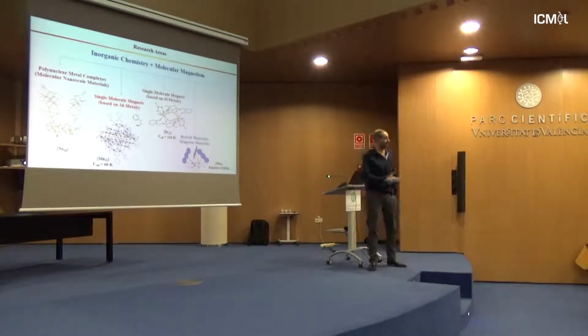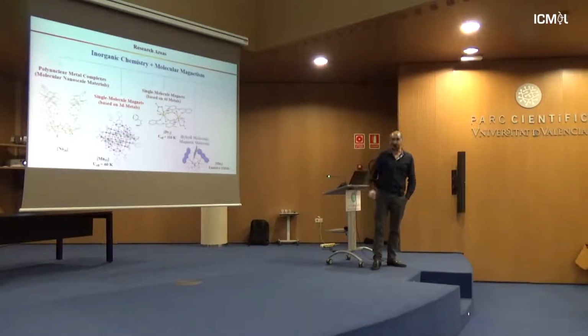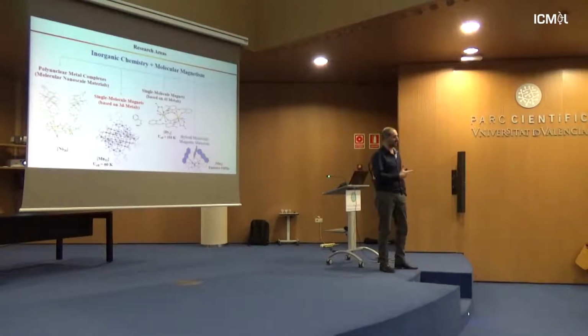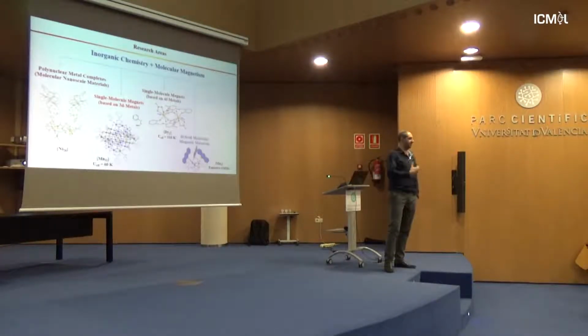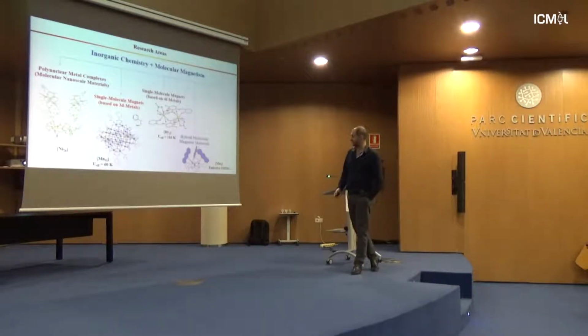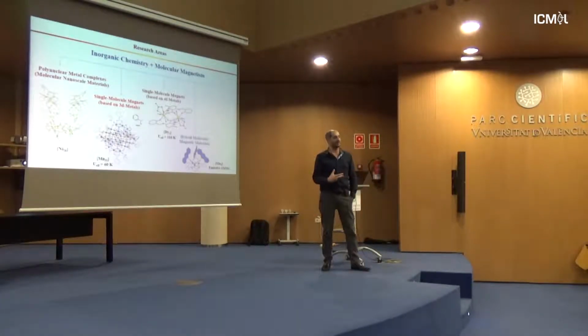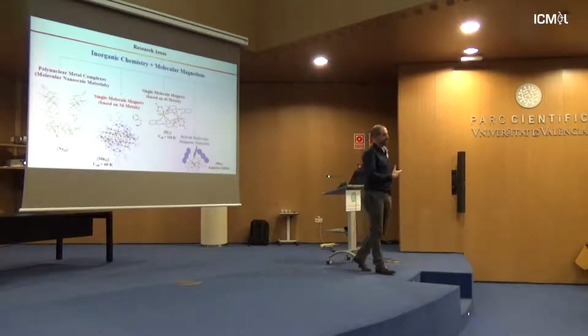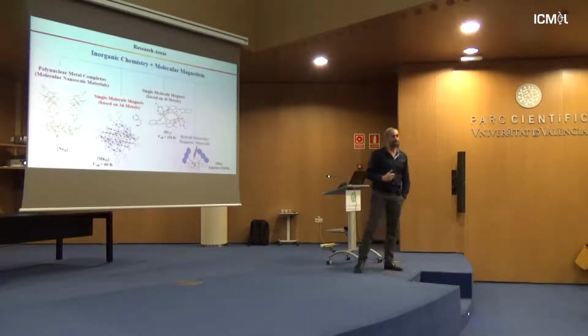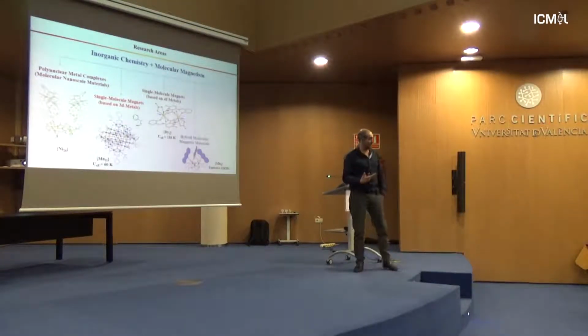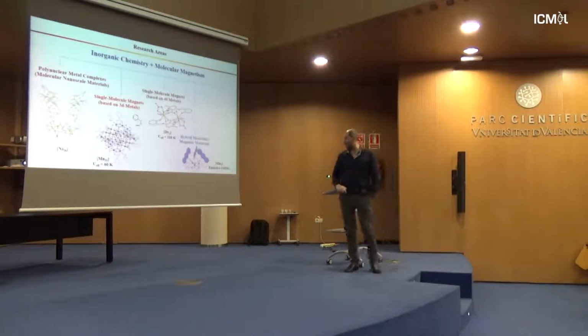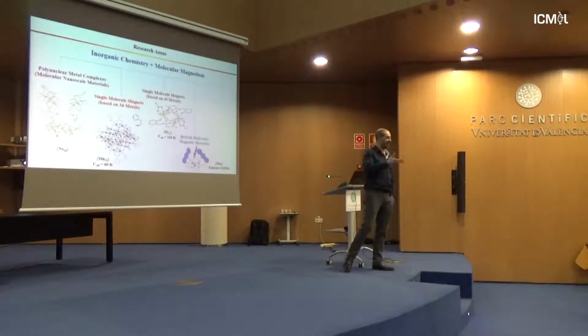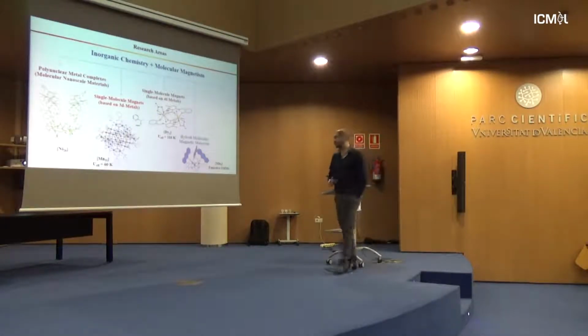And what we've found out from these compounds is that they still retain their photoluminescence properties. They emit in the red and blue regions of the visible part of the electromagnetic spectrum, while they still retain their SMM properties without changing the SMM dynamics. So the next thing that we would like to try, but we don't unfortunately have the infrastructure, is to see how we can bundle the two properties and see how we can affect one by changing the other.